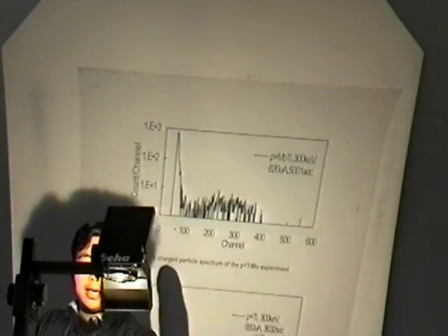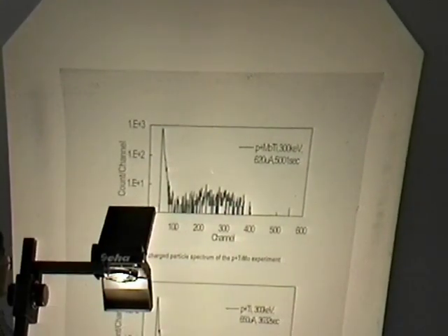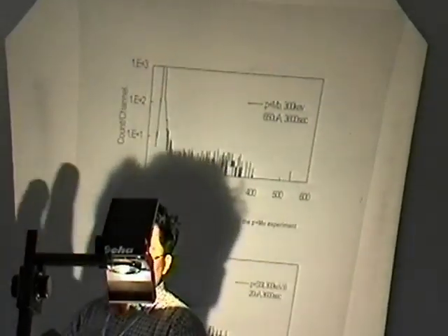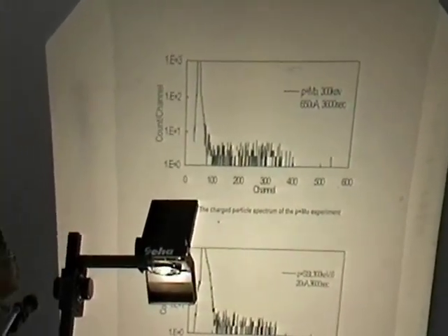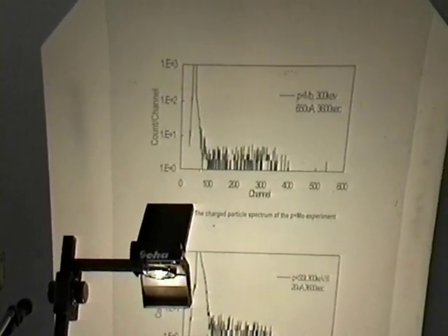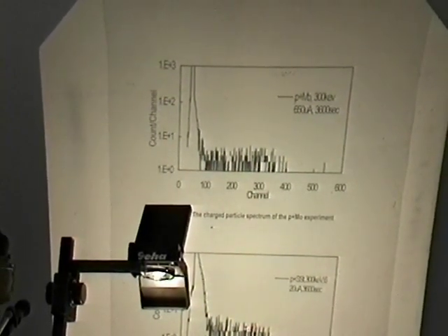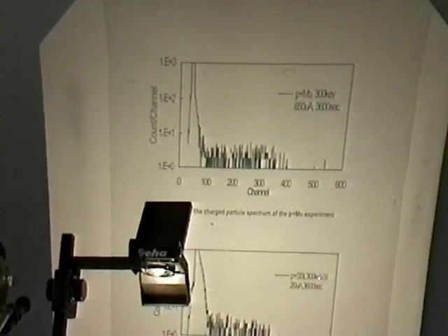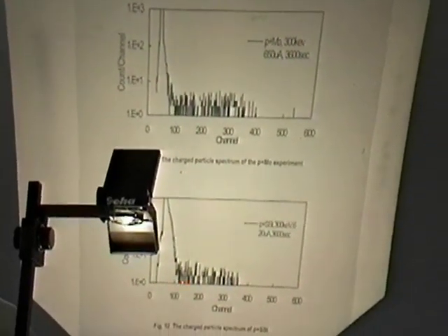And we check the background. We have used a different target, and when we use this target, we can observe only a limited number of alpha particles. And here we bombard titanium, we observe very few counts. And then we change the target. We use this target, we also observe not very much. And here we use stainless steel, and we also observe not very much.